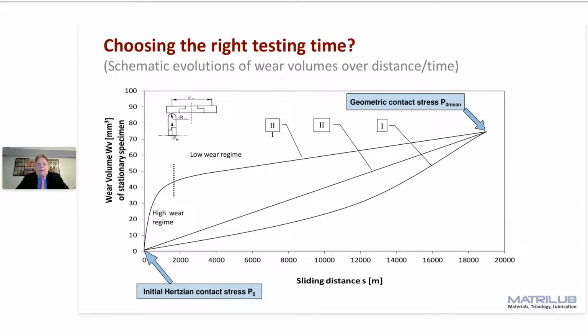If now you would have had 19 kilometers of sliding distance as test time, you would conclude all 3 couples have the same wear resistance. But this is not true. If your testing time is too short, 1,000 or 2,000 meters, you would say couple number 3 has an unacceptably high wear. We take couple 1, but this result is also not true. So I understand that everyone wants to have standardized tests, but this can be misleading in terms of selecting materials.